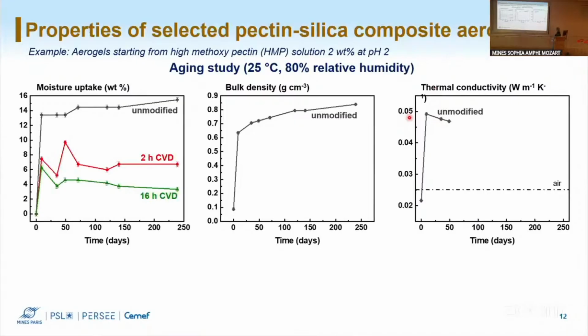When we do the deposition of the silica phase, we can see that the moisture uptake decreases a lot. So it's almost half. Then the bulk density increases slightly in the first day, but stays rather low compared to the neat pectin aerogels. And the thermal conductivity increases more substantially. This is the red line when we have 2 hours chemical vapor deposition, and for 16 hours deposition, the thermal conductivity stays nearly stable for the whole duration of the test, that was around 250 days.